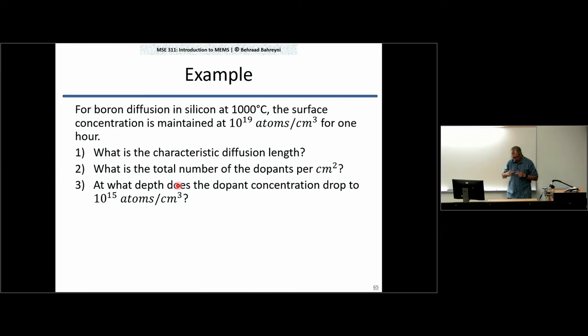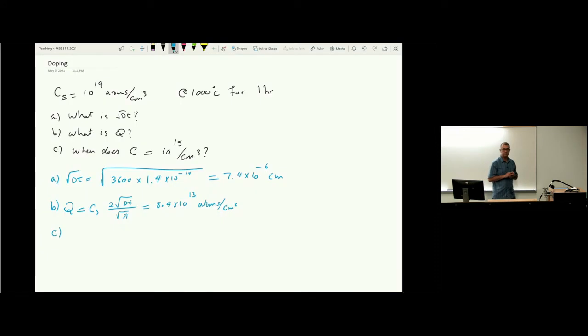What does that mean? It means that if I look down onto this substrate after my doping is done, after 1 hour of doping, and calculate all of the dopants that I see here and normalize it by the area, that will be the number of atoms. All of those dopants, if I assume they are at the surface, that's how many atoms I have. So I can actually calculate how many atoms I have inside the substrate if I want to. And the last part says, how deep should we go before the dopant concentration drops to 10 to the 15.